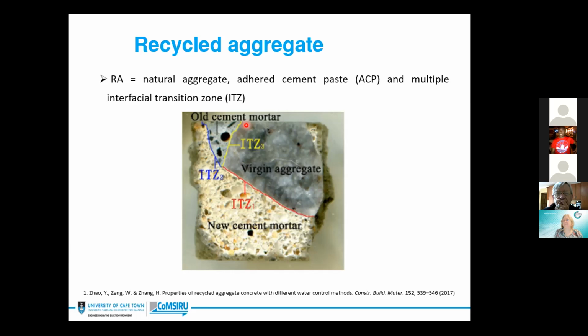So the challenge of recycled aggregate is more with fine recycled aggregates than coarse recycled aggregates. This is because the adhered mortar is significantly more in fine recycled aggregates than coarse recycled aggregates. As a matter of fact, the percentage of adhered mortar increases as aggregate size reduces.